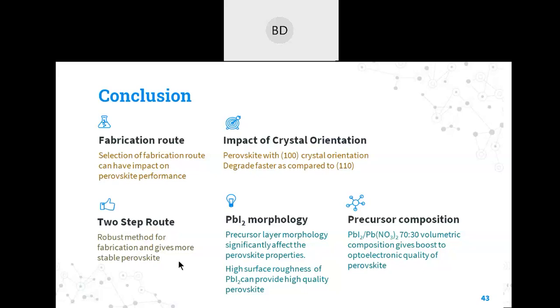And if you have a PbI2 with higher surface roughness, it can provide more active sites for perovskite conversion. We understood that if you add a 70-30 volumetric ratio of PbI2 and lead nitrate, it gives a significant boost to the optoelectronic properties. So with this combination, we understood that if you take a two-step route, take a nitrate precursor composition, or change the PbI2 morphology by temperature changes, you can get a stable perovskite as compared to the other methods.